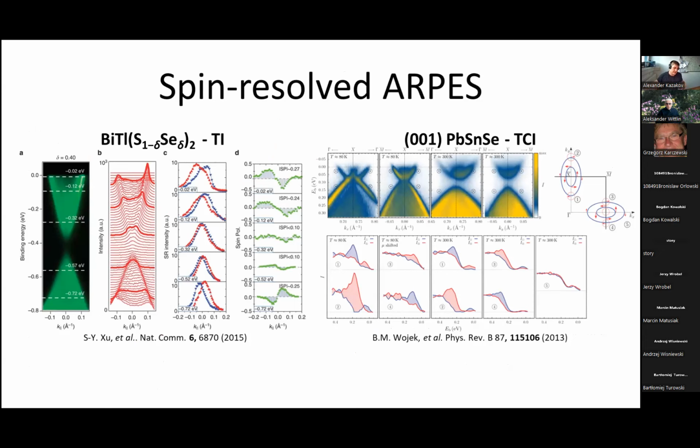These results are somehow aligned with several results on spin-resolved ARPES measurements. The quantized Berry phase usually means that there is a certain texture in the orbital or spin momentum in the reciprocal space. So it means that such texture is present in both topological and non-topological films.